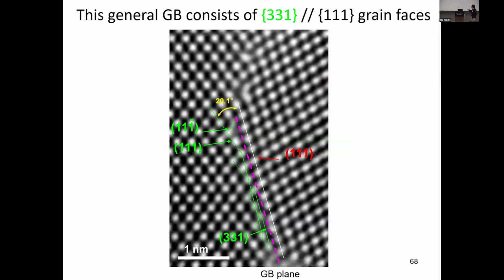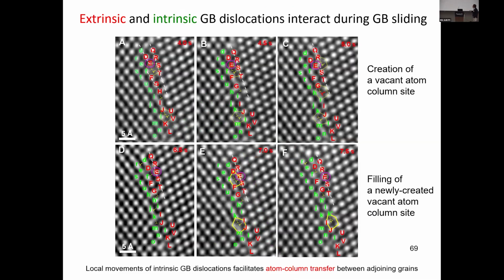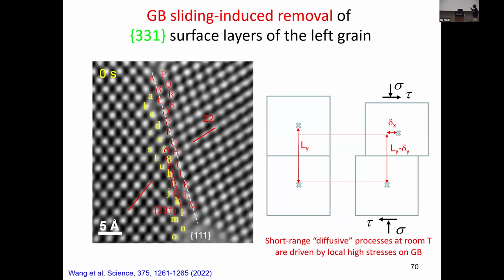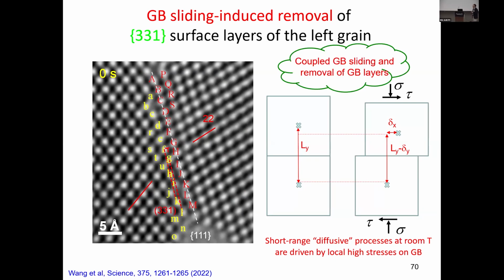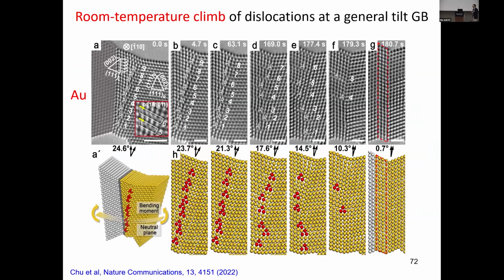As a result of this mixing, these two surface atomic layers disappeared during this deformation process. But those atom columns didn't disappear. They actually transfer into the surface layer of the right grain. So those detailed atomic processes can now be directly visualized and understood with this in situ capability. Without going into further details, I just want to say that it can significantly impact the macroscopic deformation, causing, for example, plastic flow dominated by the grain boundary, and that can also cause, for example, creep deformation. So this kind of unexpected process is mainly driven by the very high stress at the grain boundary.